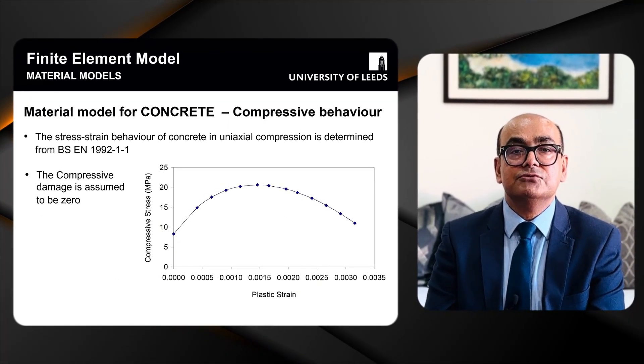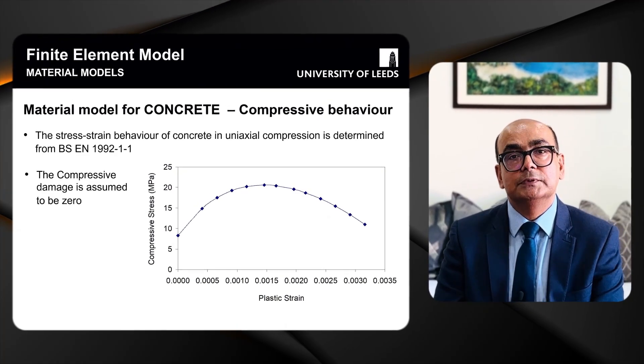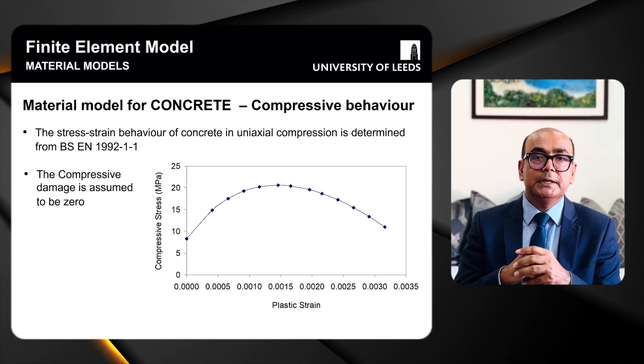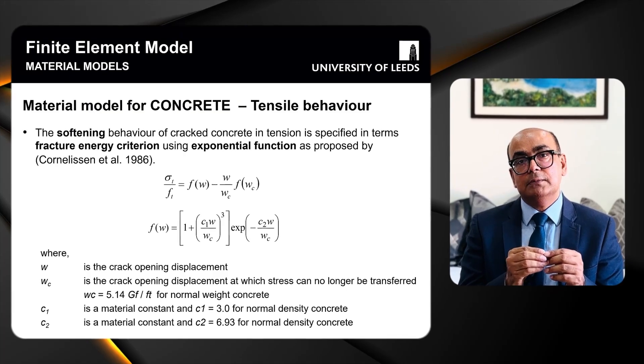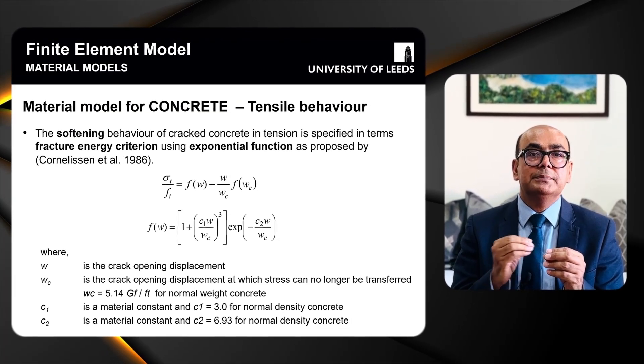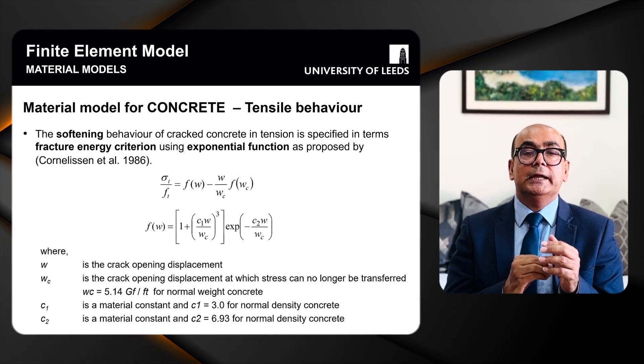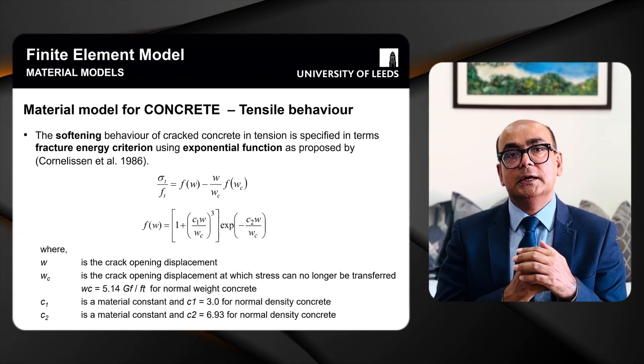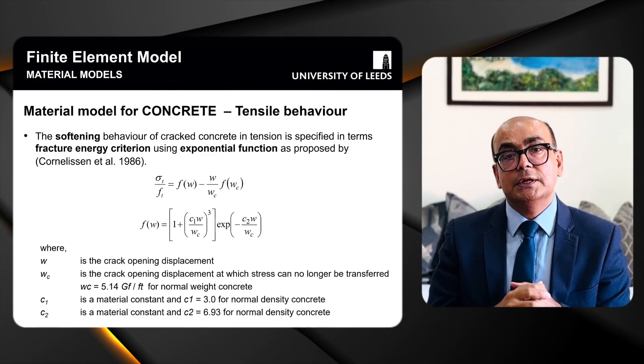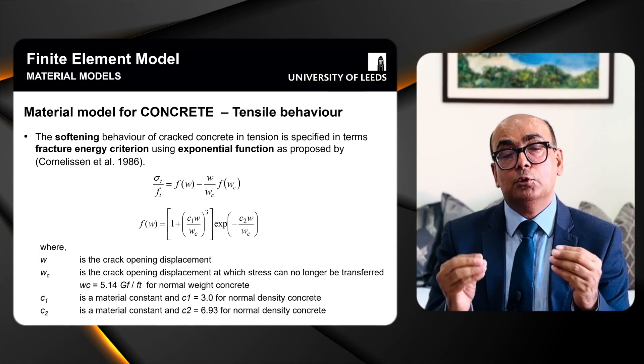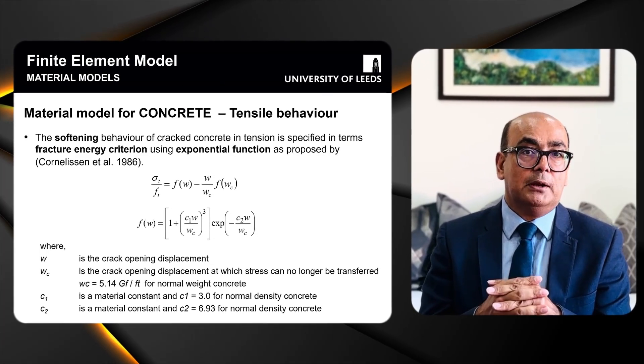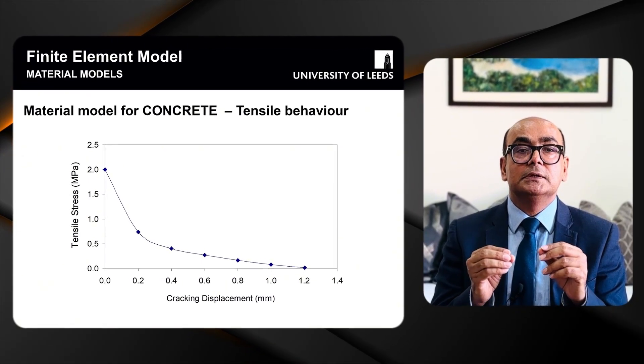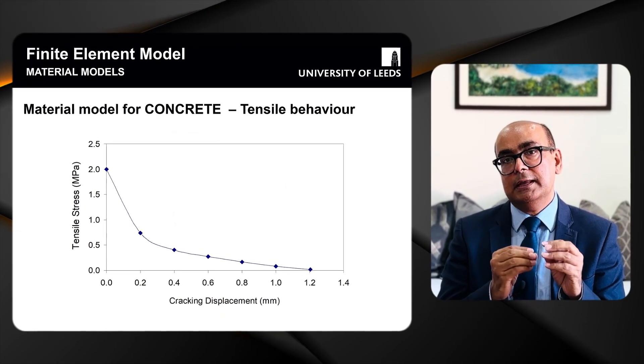The compressive stress-strain behavior is determined from the model mentioned earlier, with further details of the equations given in the paper. Tensile behavior is very important — we must model the softening behavior of cracked concrete in tension. We specified it in terms of fracture energy using an exponential function as proposed in the referenced paper, using crack opening displacement parameters derived from those equations.